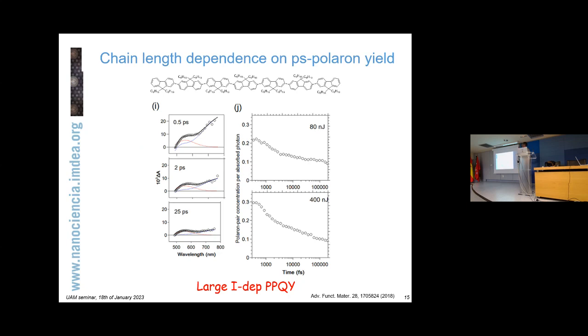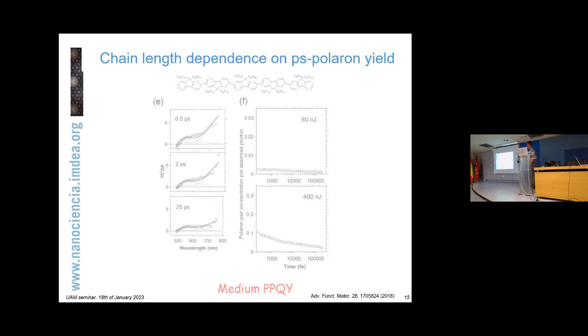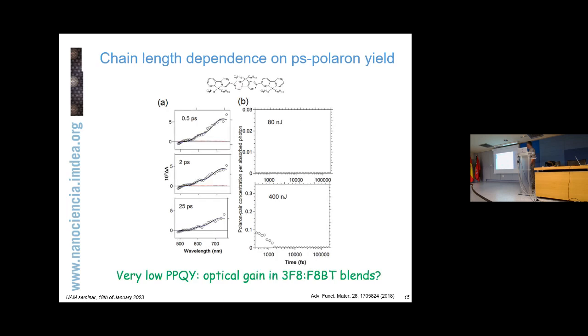As you see, you still have a very large concentration of polarons being generated. But as you start to reduce the chain length, you can see the concentration reduces. You have a small concentration at 80 nanojoules, but with the fluorene trimer at 80 nanojoules, it disappears. You get a fast transient signal that the modeling interprets as fast charge recombination, and no polarons at all. So really using short units helps solve the problem.